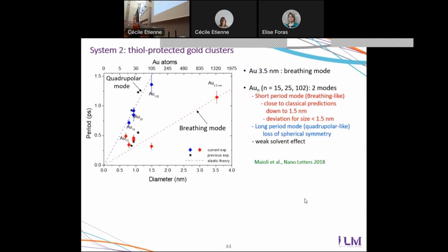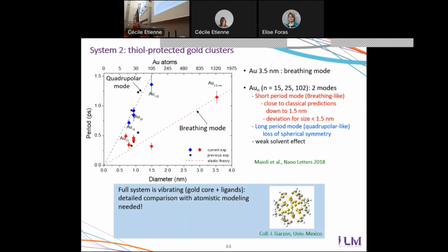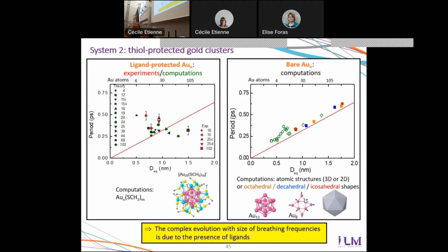Focusing on the breathing mode, the same as before. For the largest particles, it's still along the same line as before. But for all small nanoparticles, this time there is some deviation. So the question is, do these deviations arise from a breakdown, a collapse of the laws of elasticity at the nanoscale, or do they arise just because of the presence of ligands around the particles, which cannot be avoided with this synthesis? So this was answered using numerical simulations by our Mexican colleagues.